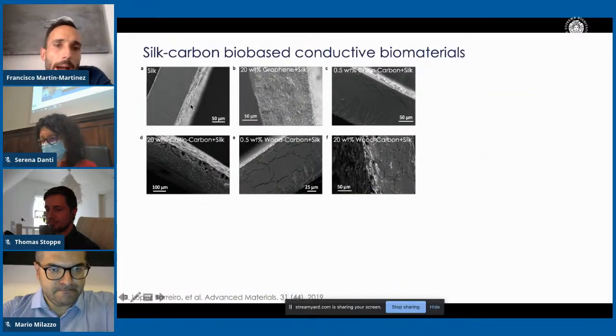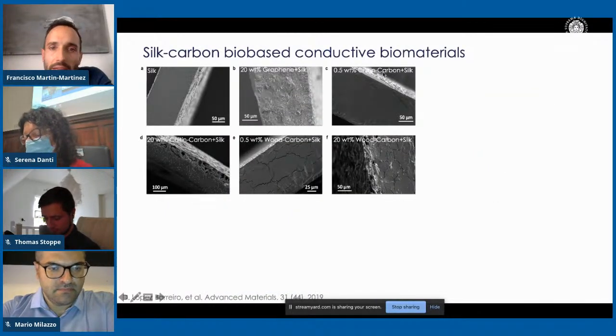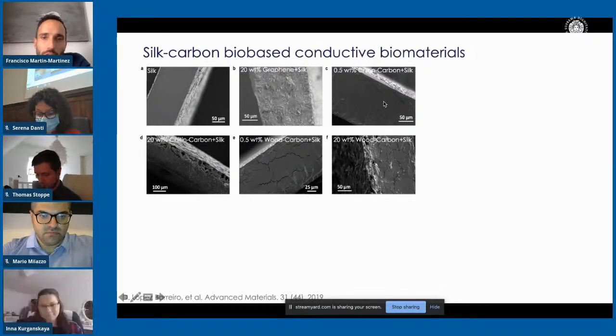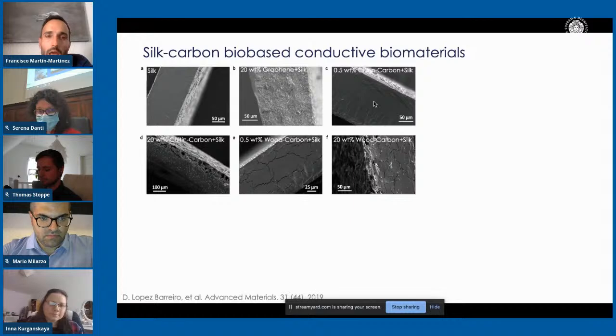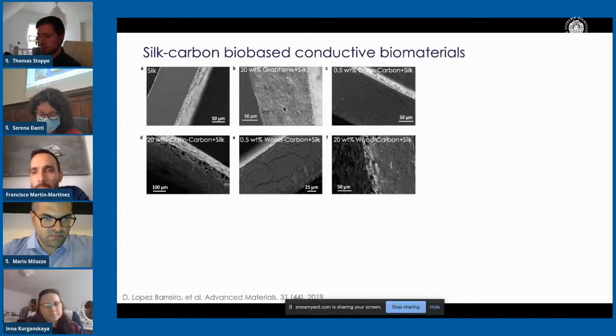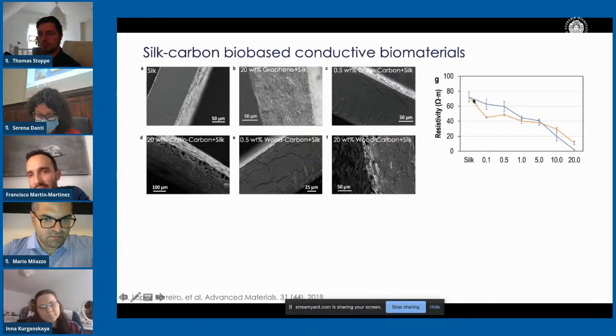You can see how, if you compare silk with graphene and then with the bio-based carbons, the absorption for those from chitin is very good. So thanks to the nitrogen, it integrates very well with silk, which is something that doesn't happen with graphene. It was observed with graphene oxide, but not with graphene. You can see how the resistivity goes down as you go from pure silk to increasing percentage of chitin-derived bio-based carbon. So it actually becomes more conductive.